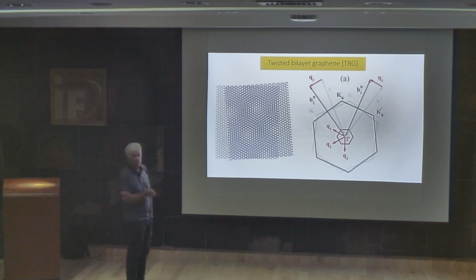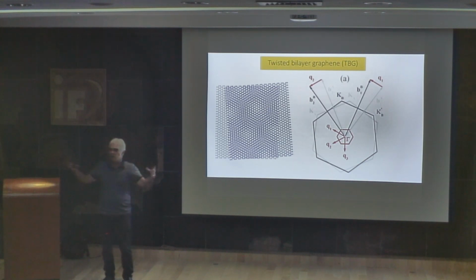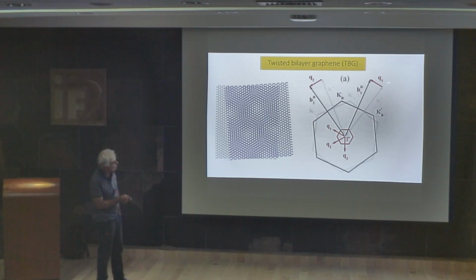Now, let's go to the reciprocal space. Every time we have a superlattice in real space, in the reciprocal space we have a small thing. For example, here I'm putting in gray the Brillouin zone of one layer, and in black the Brillouin zone of the other layer, okay? And you can see that Q1, Q2, and Q3 are the vectors that connect the reciprocal lattice vectors of the gray layer to those of the black layer. This Q1 is the vector that connects